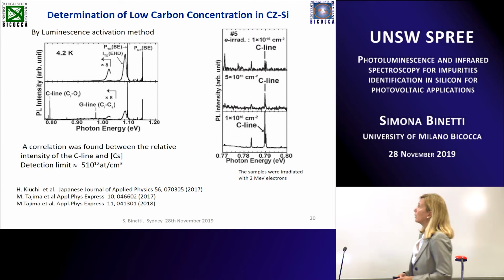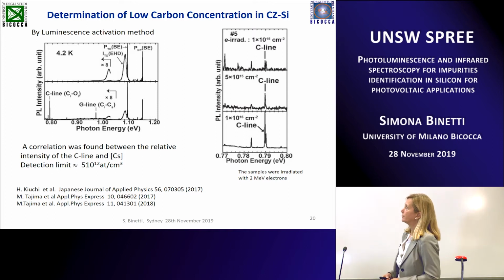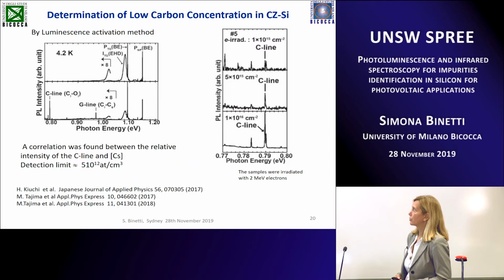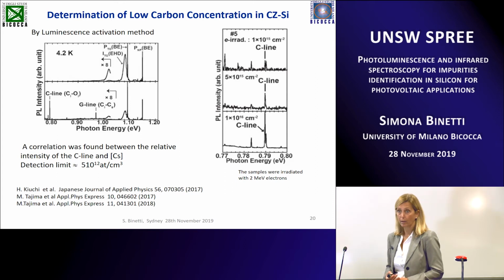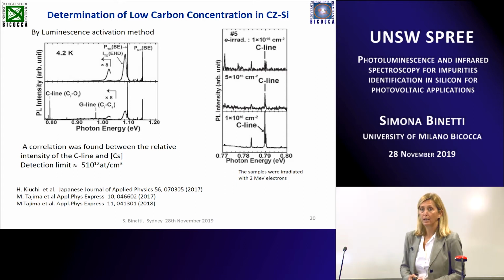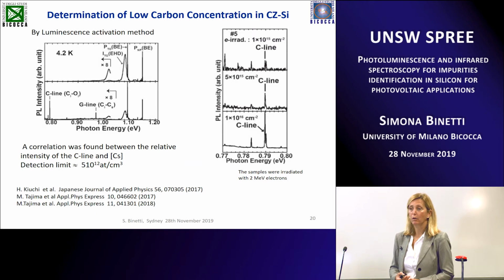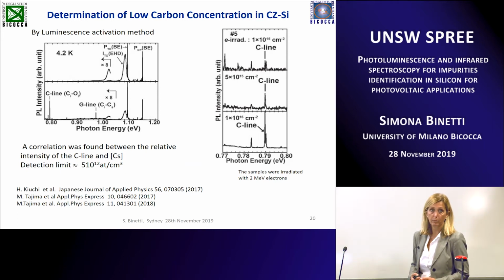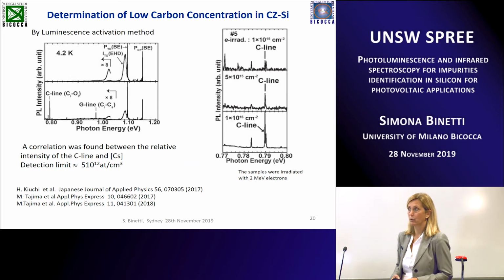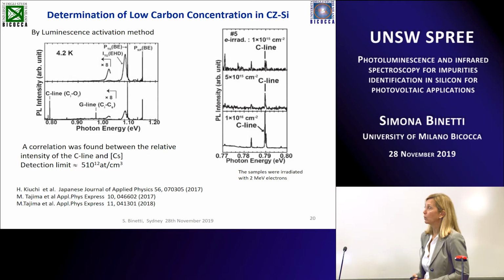By detection of the C line, it's possible to have a quantification of the low carbon concentration in your sample. Because you know that in the case of solar grade silicon and silicon for photovoltaics, the concentration of carbon is always under the detection limit of infrared spectroscopy, but sometimes it's very important to have a quantification of this concentration, because carbon is in your material and can form complexes after some thermal treatment or process.